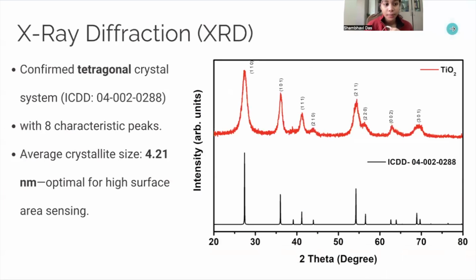such as XRD. This showed us 8 different characteristic peaks with a confirmed tetragonal crystal system. The average crystallite size was 4.21 nanometers, which is optimal for high surface area sensing.